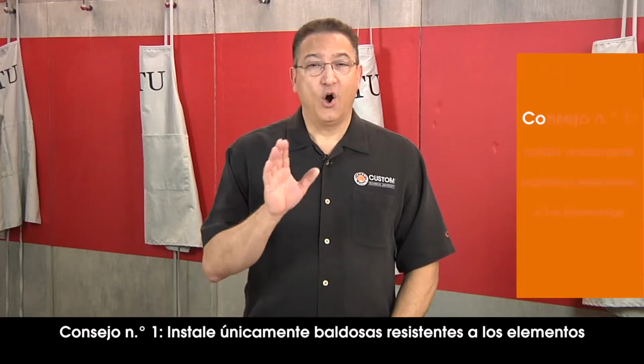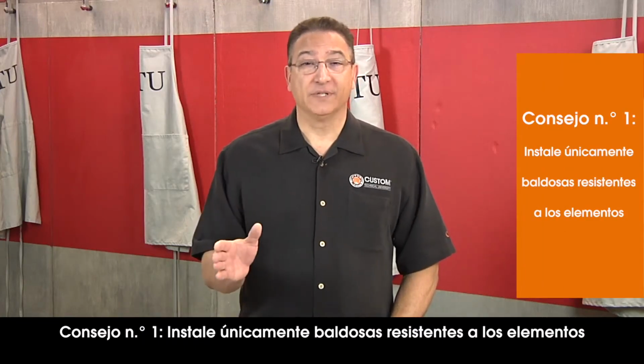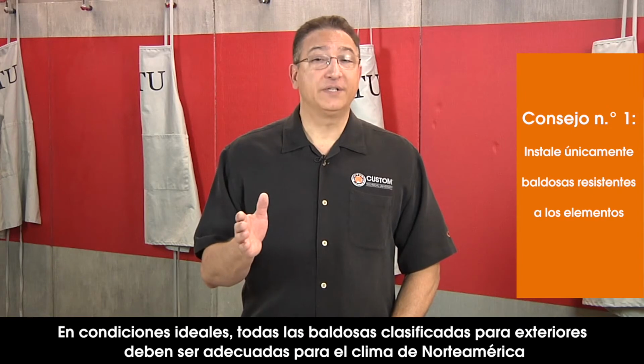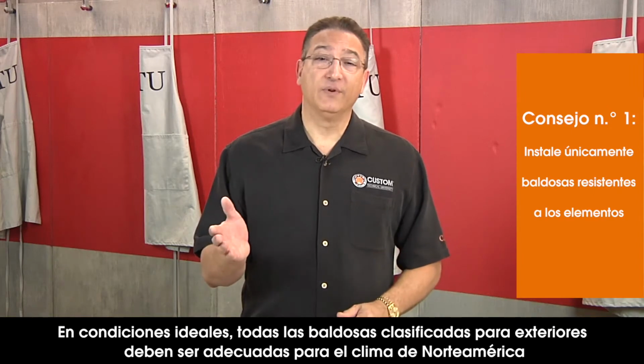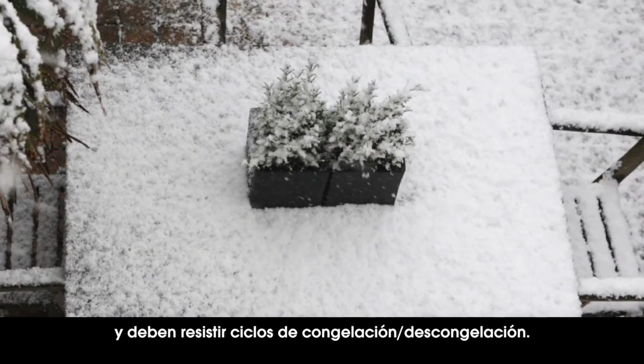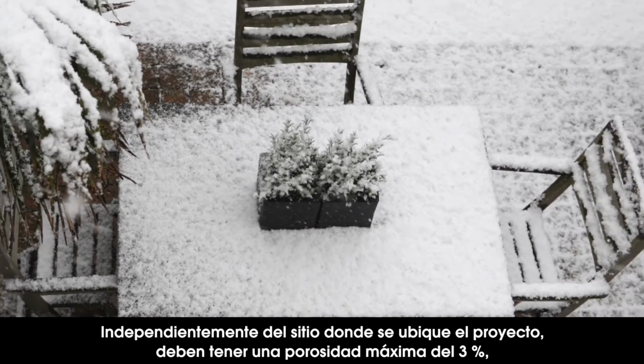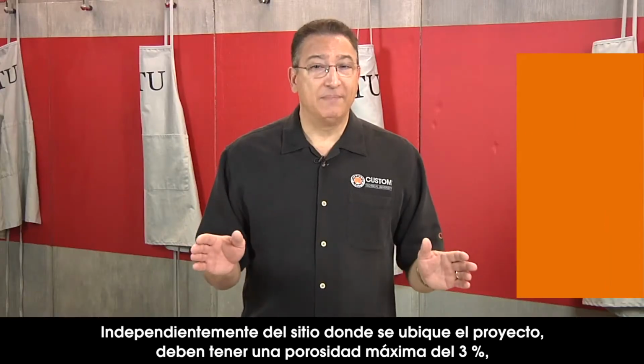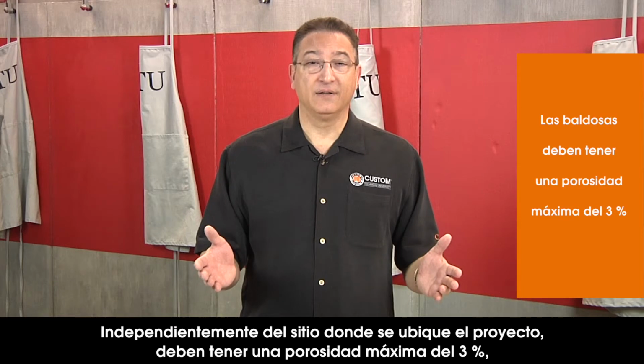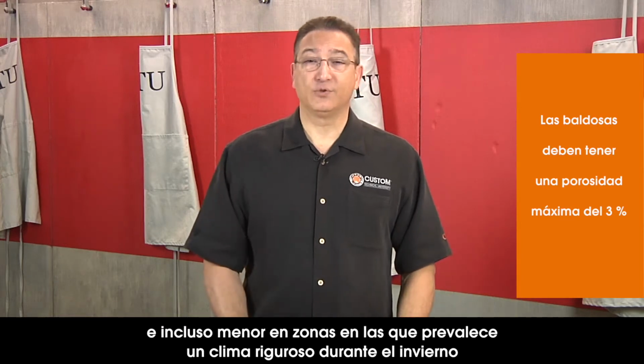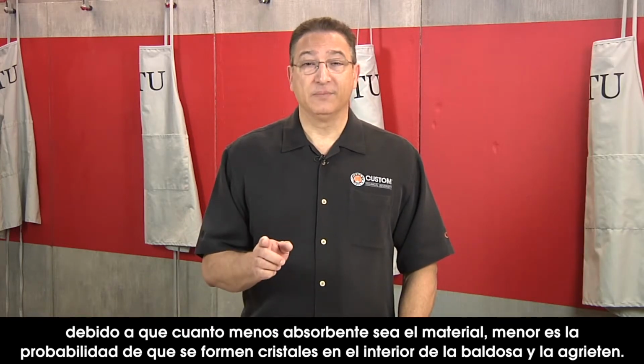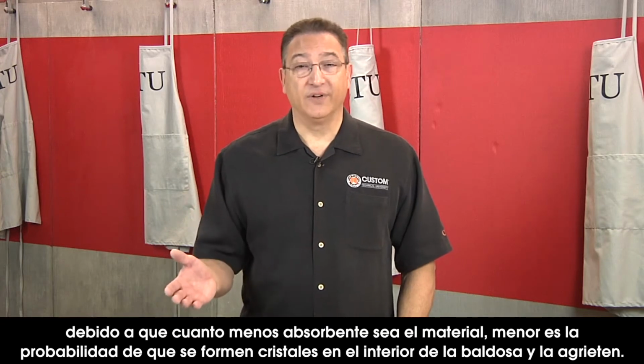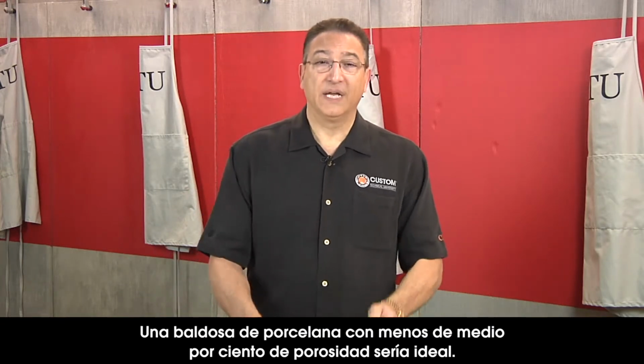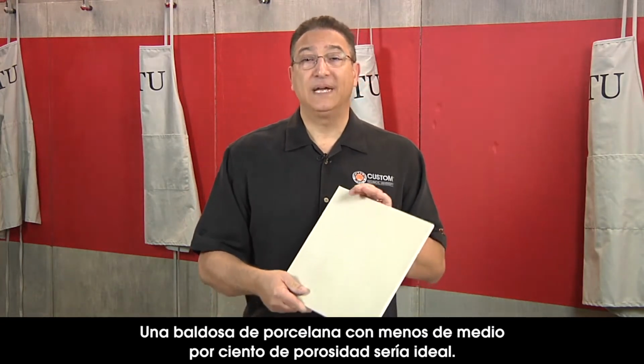Tip number 1, only install tile that can hold up to the elements. Ideally, all exterior rated tile should be appropriate for weather in North America and can survive the freeze-thaw cycles. Regardless of where the project is located, tile should have a maximum porosity of 3%, even less in areas where there's harsh weather. The less absorbent the material, the less likely the tile will fail. A porcelain tile with less than 0.5% porosity would be ideal.